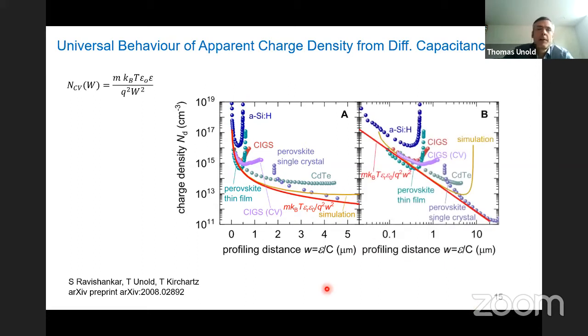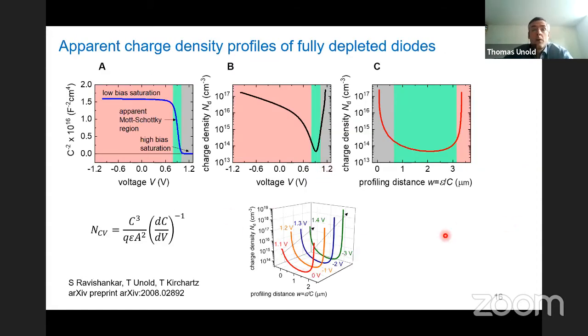And you can also plot it double logarithmically. You can see in double logarithmic it would be just slope two or one over two. And you can see that basically it's a tangent to all this data here. So none of the data drops below that. What does it say? I mean, you already can see that, is it really true that in no device whatsoever there would be a lower charge density closer than, whatever, 0.5 micrometers to the interface? Probably not, right? So to further understand that, we can look again at what happens here.